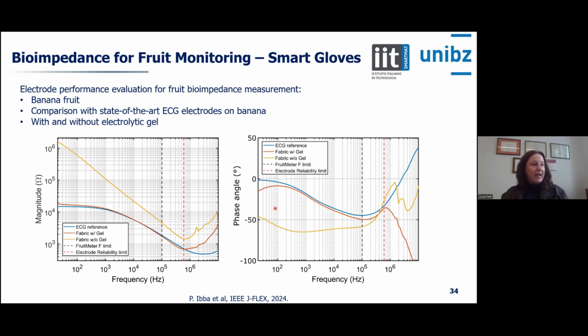We did all the electrical characterization. So what you see here is magnitude and phase of the ECG reference electrodes. Of course, that's the golden standard in bioimpedance. The fabric with and without gel. So that's a big topic, the use of gel. Again, we would like in the end to have something without gel, completely edible, ideally. So this is also, I think Mario also showed recently some nice edible electrodes, macaroni, for bioimpedance. So that's a big topic. If you want to have good measurements, you still need to rely on gels. And that's a big issue.